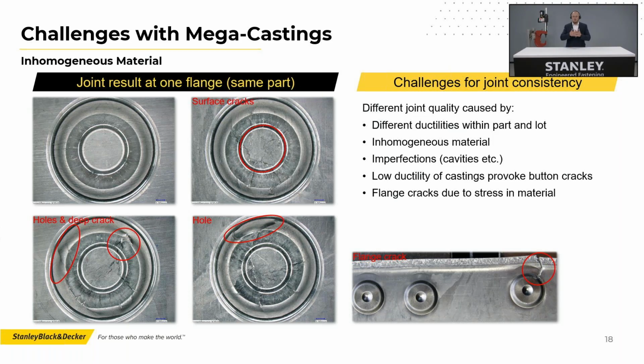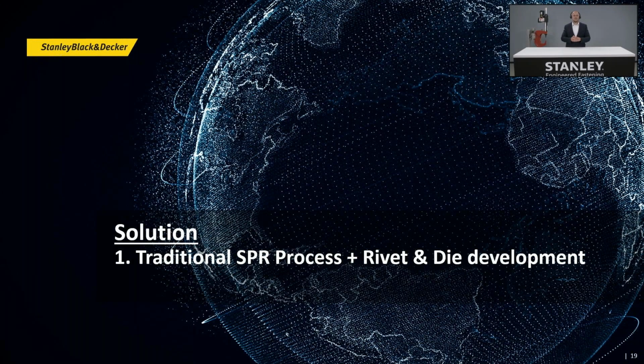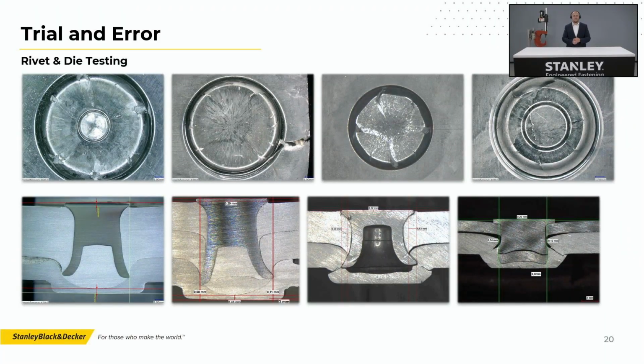So how do you work and how do you deal with these imperfections and these challenges when you want to join them at a consistent rate, to reach the right CPK values and be okay and don't have high ppms? So the first thing that you need to do is you need to do a lot of testing and you need to do a lot of failing, meaning we have done over 1,000 tests on these materials, different ones, and we saw many different failure modes. So you can have flange cracks, all the problems that you have seen in the slide before. You can have holes, you can have surface cracks, you can have a complete crack where the button falls off the sheet. You can have insufficient interlock, you can have all of these issues.